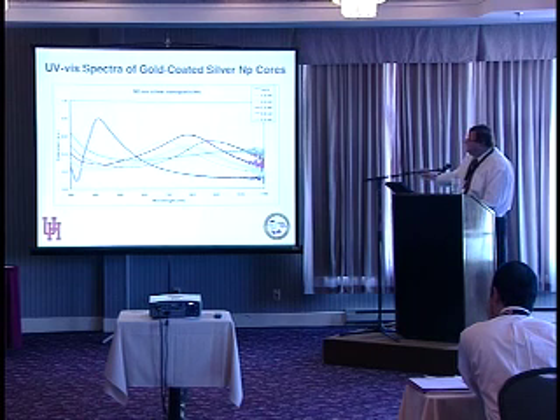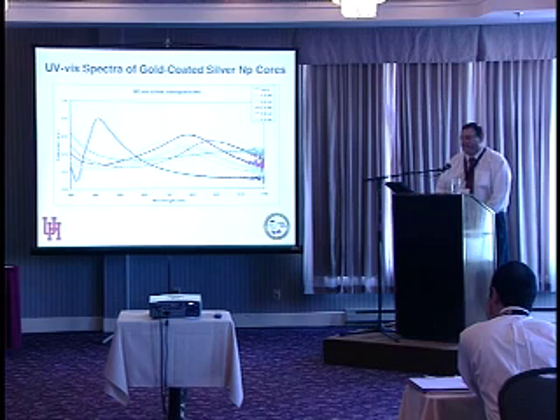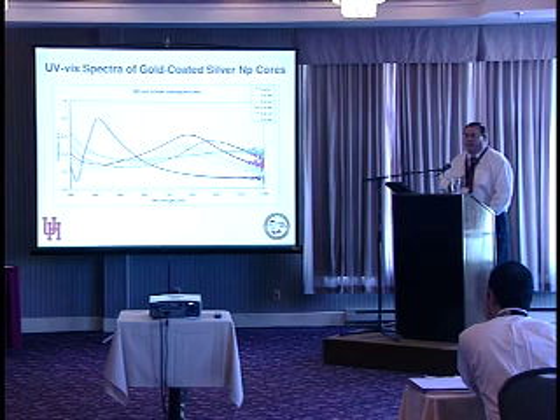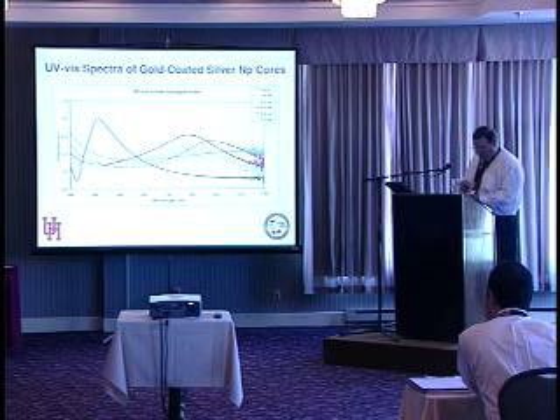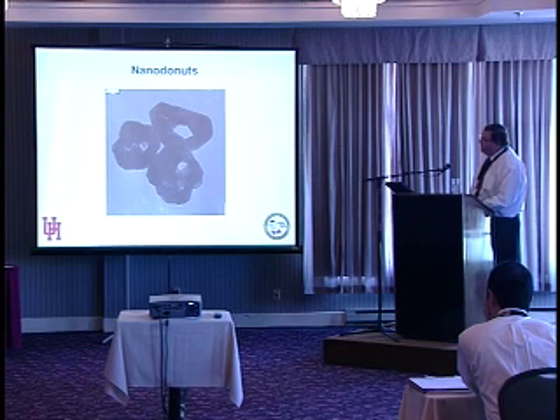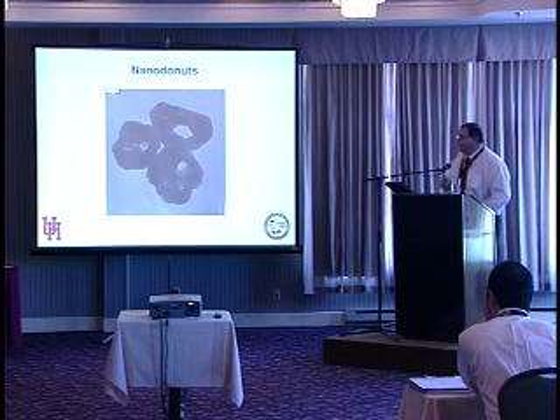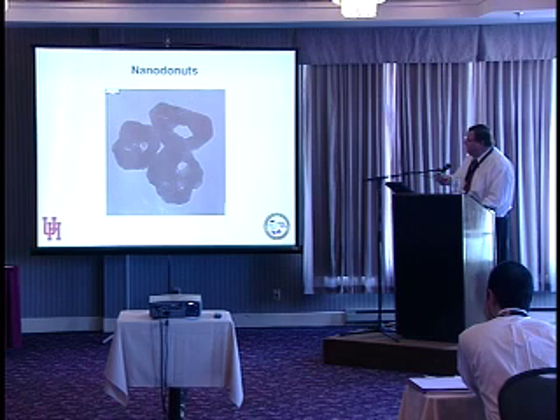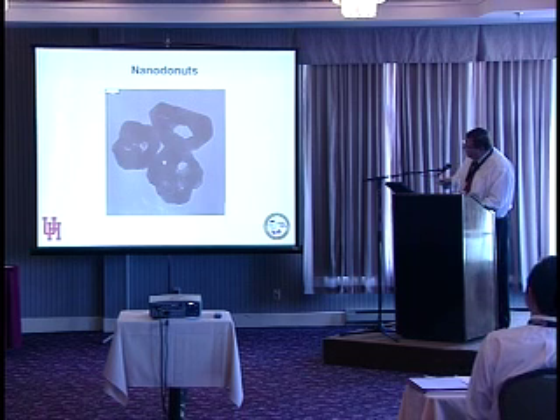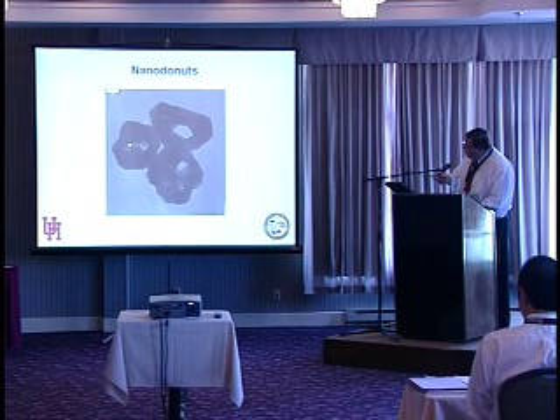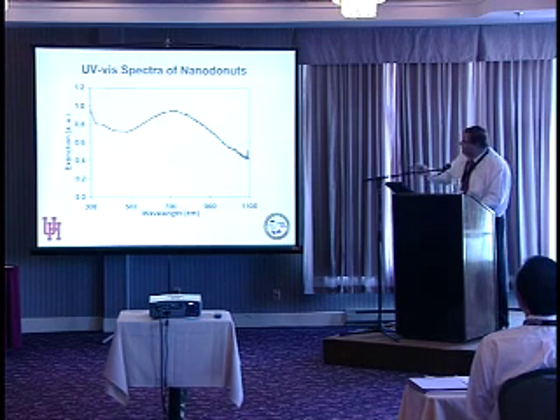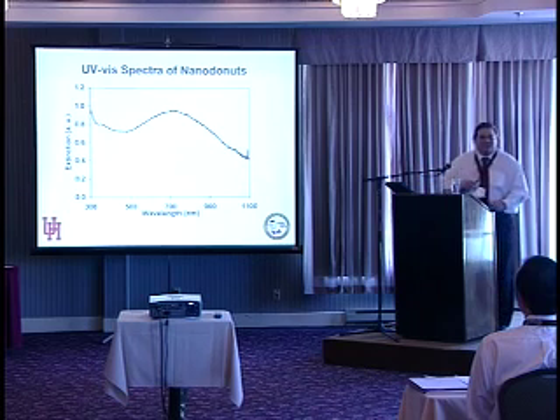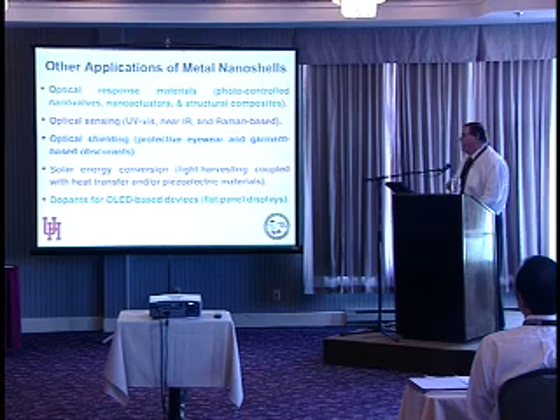So an important thing to note is that for the older technology nanoshells, it's hard to get below 100 nanometers in overall dimensions. These particles we can make down to about 40 so far. So we can get to much smaller dimensions and more access to different biological systems. We've also made some particles that we call nanodonuts. And you can see here's the nanoparticle with the hole in the middle. These nanodonuts also have an absorption in the near infrared, and we're exploring them for use in various applications.